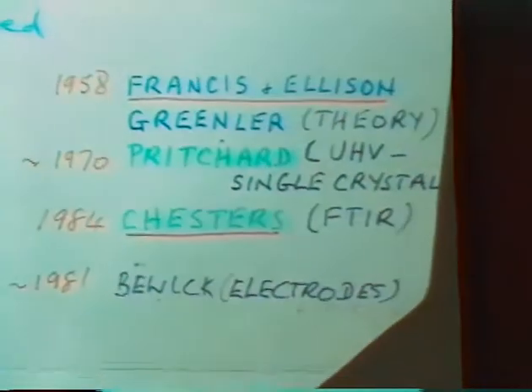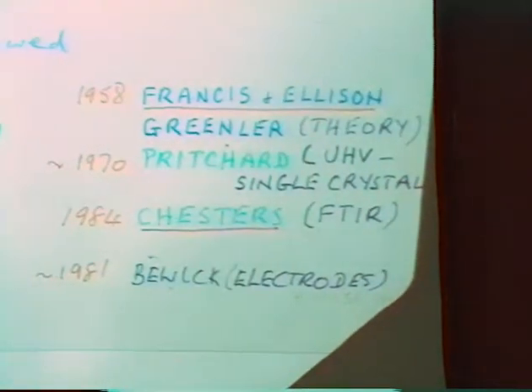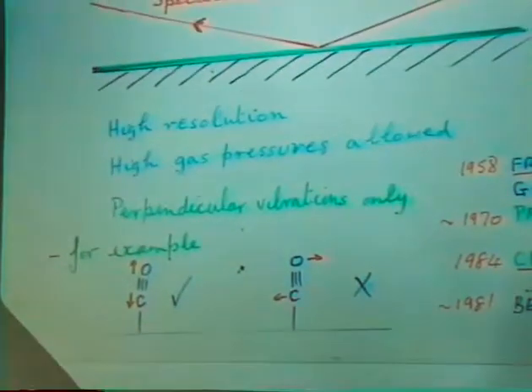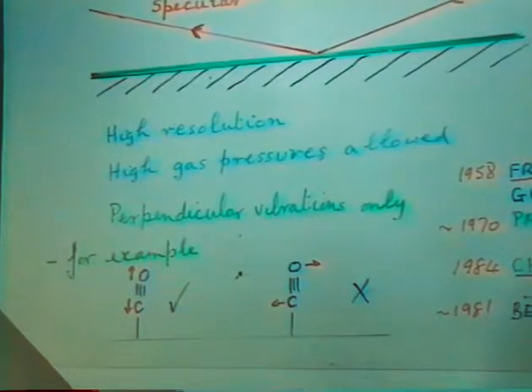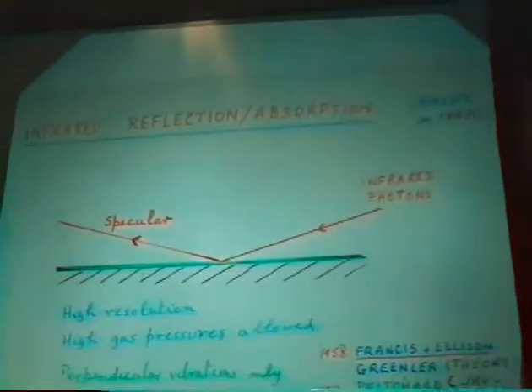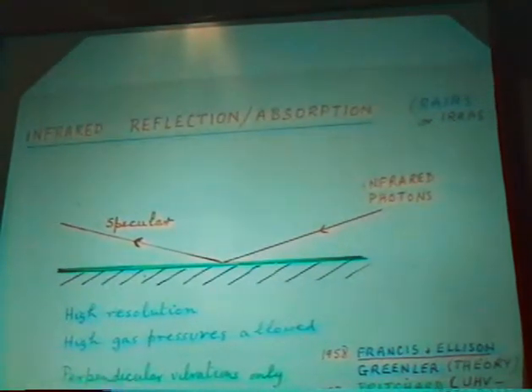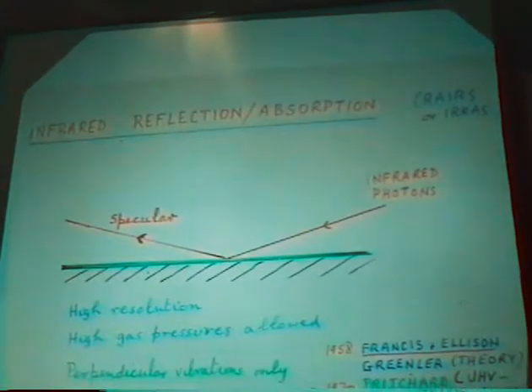At that stage, reflection absorption infrared spectroscopy received a boost, partly because of the success of electron energy loss spectroscopy. And my colleague Michael Chesters applied FT techniques to it, and now we could begin to get spectra not only from adsorbed CO, as others had early, but also from hydrocarbons on surfaces. Here, of course, the metal surface selection rule is strict, and we can only see the modes which are perpendicular to the surface.